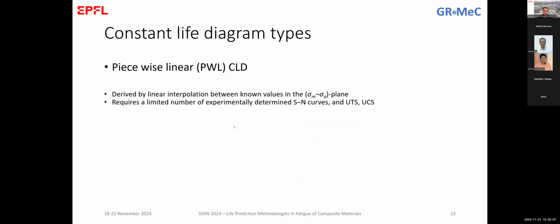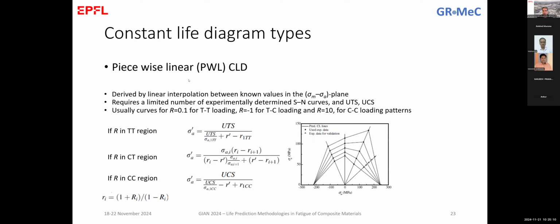So other constant life diagram types, it's the typical piecewise linear, and we call it piecewise linear because we draw the iso lines by connecting linearly the points in the different SN curves. Remember, the SN curves are the radial lines corresponding to different numbers of cycles. So this curve might show 100 cycles for all the loading cases. This curve might be 10,000 cycles. This curve might be 1 million cycles for all the cases that have been investigated.